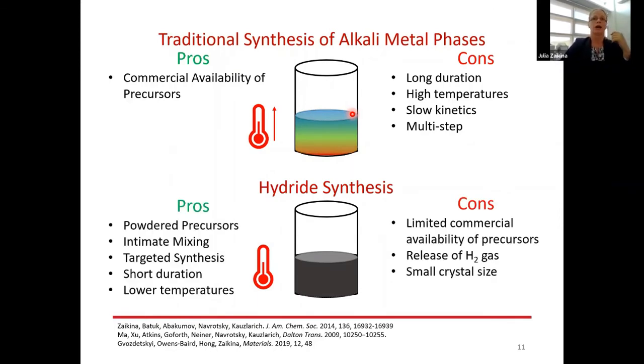and our reactions are always faster. So the traditional solid-state synthesis reaction takes several days, oftentimes several weeks. In our case, it's several hours. So you put your reaction into the furnace in the evening, and you already would know the outcome of this reaction the next day. So it's a lower synthetic temperature, which allows us to target those kinetically stabilized phases. The reactions are short. We also can target particular composition in the compositional phase space.